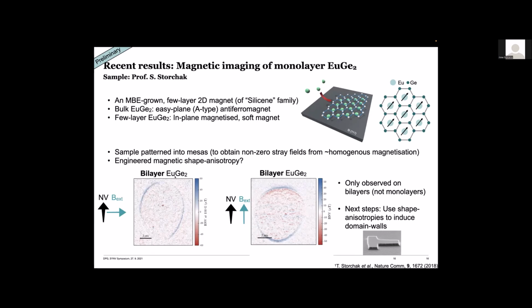So in this experiment here, we have this ellipse where we apply a magnetic field along the short axis of this ellipse. So if the magnetization was free to rotate in this layer, it would just follow this magnetic field. But that's not what we observe. Instead, we observe that the magnetization seems to be slightly canted here, or not canted, but rotated in this orientation. And our present tentative explanation is that this is due to shape anisotropy introduced by this elliptical shape. But again, this is something to be verified further.